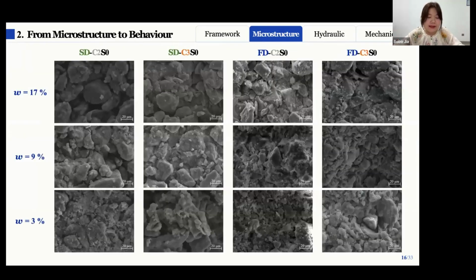And the parallel SEM images provide a clearer illustration of these changes. For the initially compacted samples, SDC3, with higher sodium chloride content, shows stronger interparticle bonding than C2. The particles appear larger and more compact. It indicates a more pronounced aggregation effect. And when the water content decreases to 9, the structure exhibits slight shrinkage. However, the crystallization threshold has not yet been reached, so the pore structure does not change significantly.